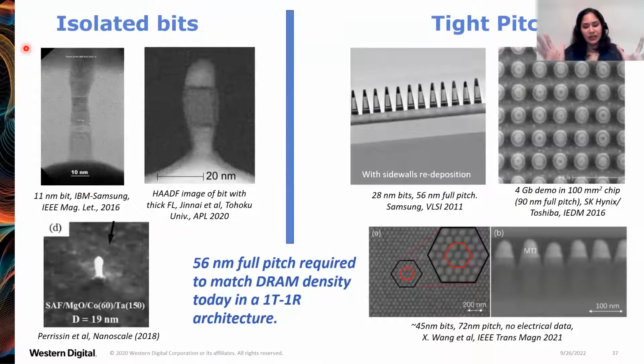Looking at the MRAM studies and literature, there are a lot of great reports of very good performance of MRAM bits that are very small. For example, from the IBM Samsung team, this is an 11 nanometer bit. Here are a couple of examples of 20 nanometer diameter bits with good performance, but these are isolated bits, meaning you have your MRAM pillar here, but there are no neighbors close by. There are very, very few reports of arrays of MRAM bits at tight pitch, and the reason is that they're very difficult to fabricate.